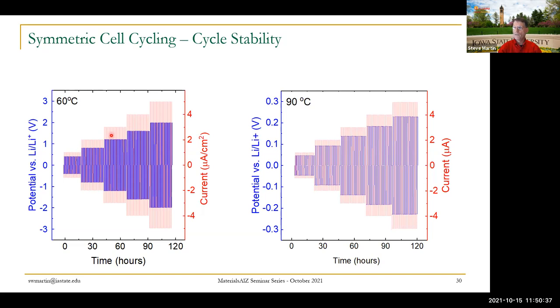We cycle it at 60 degrees Celsius. We cycle it at 90 degrees Celsius. Our currents now go from nanoamps to microamps because of that exponential dependence on temperature, but they're perfectly flat. They're just ohmic in every respect, meaning that the glass is perfectly stable in cycling.